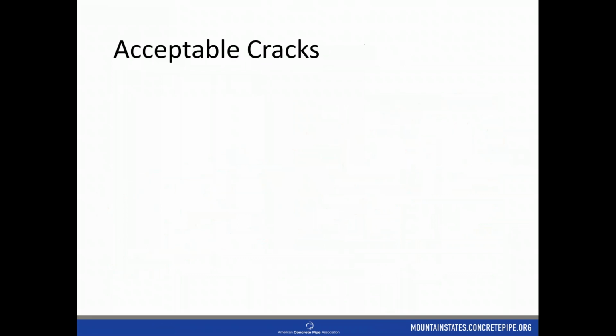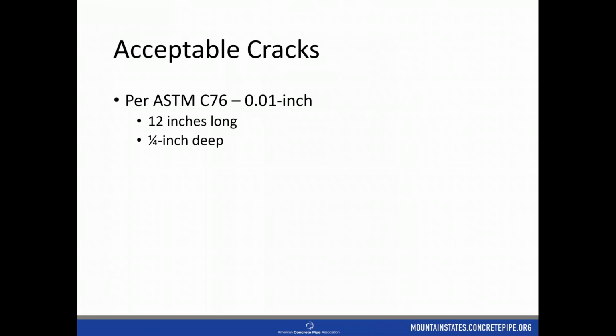What is acceptable? We talked about that. Cracks per ASTM C76, 100th of an inch. Now, the definition per ASTM C76, so that you know, a 100th of an inch crack is one that is at least 12 inches long. If it's less than 12 inches, if it's only 6 inches long, that wouldn't even be considered a 100th of an inch crack. This is one that is 12 inches long, and you're able to put a 100th of an inch leaf gauge inside the crack at least 1/4 of an inch.